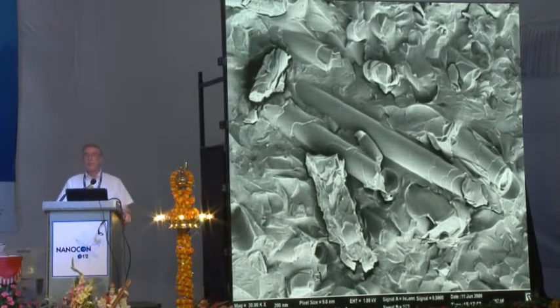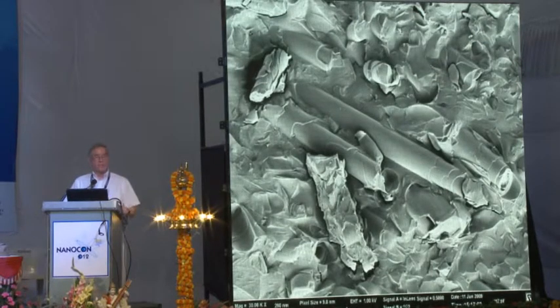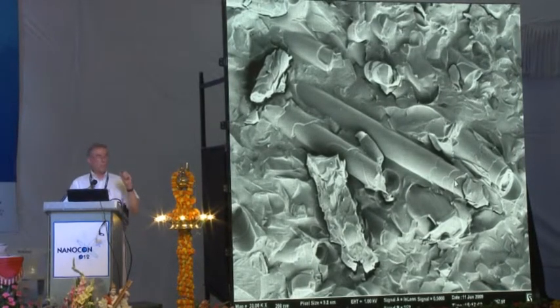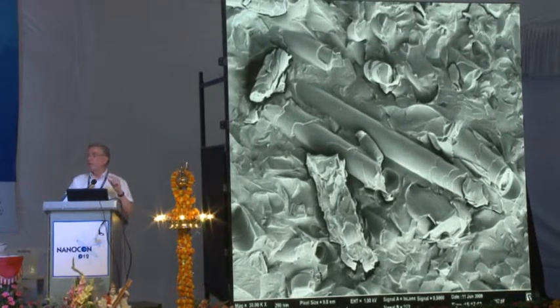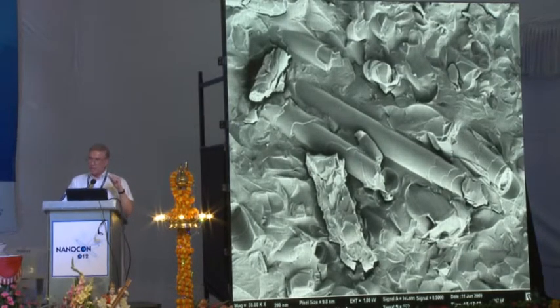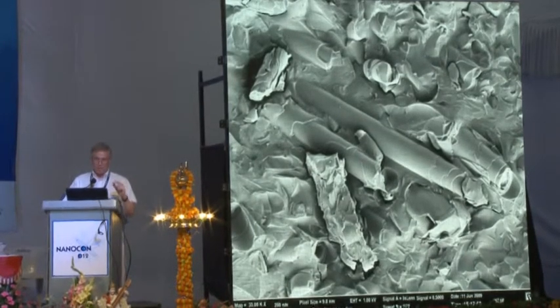So this is an ointment, a medical ointment, and what you see here is a structure that is called a cochleate. You see, this is a cochleate. What you see here is a bilayer of lipid which is wrapped around itself. And if we go along this cochleate, you see here a step, and then another step, and then another step. Each step is a bilayer of lipid, a swollen bilayer of lipid, which is about 7 nanometers in thickness.